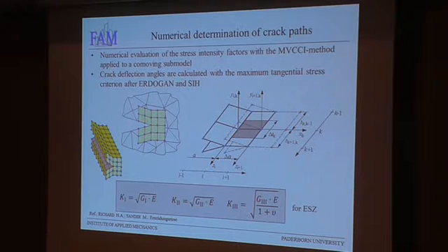For the numerical evaluation of the stress intensity factors, the modified virtual crack closure integral method is applied to a co-moving submodel, as you can see here. And the crack deflection angles are calculated with the maximum tangential stress criterion after Erdogan and Sih.